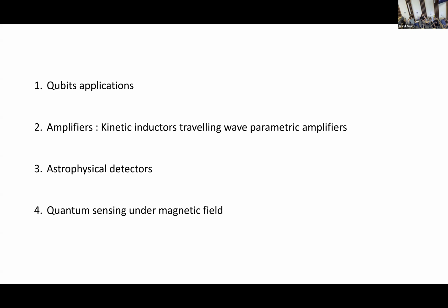But do you have an idea what this seconds scale is, because often there are multiple times in the relaxation of quasi-particles, so this very long scale could be associated to what? Well, it is attributed in the paper on granular aluminum to having very long-lived trapping states. But what these are, I guess, is anybody's guess. Aluminum might be on the millisecond scale, and when you move to granular aluminum it gets orders of magnitude longer. But also in different materials, so you can't say it's the same mechanism. It's something that at least I've met in different materials: this very fast time, then a second time, and then there are always these tens of milliseconds, hundreds of milliseconds. Material related, but sort of, yeah.